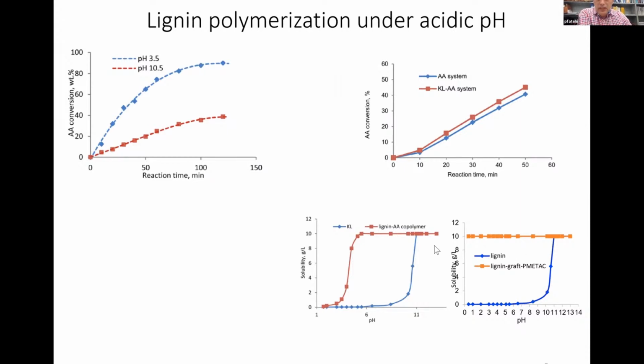So when we use, for example, acrylic acid to produce anionic polymer, the water solubility of polymer improved to pH around 4, and it dropped because the carboxylic group we have on acrylic acid has a pK of 4. When we did our polymerization with sulfonate containing monomers, we had the water solubility across the board, even at pH 1. When we had cationic one, we had 100% solubility at any pH we wanted.